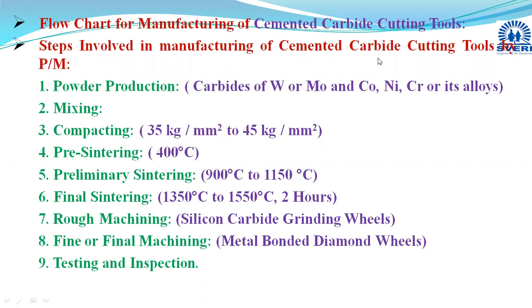Then now, how are these powder particles manufactured? We have discussed in our previous session, you can refer to that YouTube link, that these tungsten, molybdenum and cobalt powder particles, or these chromium powder particles, are manufactured by using the reduction method. We are going to use chemical processes for manufacturing these powders, in which we use the reduction method, meaning from their respective oxide compounds, tungsten oxide or molybdenum oxide. Tungsten will be obtained by reduction of tungsten oxide by using carbon or hydrogen in a reducing atmosphere. From tungsten oxide, tungsten particles are obtained and their respective carbides are formed, and that we are going to use.